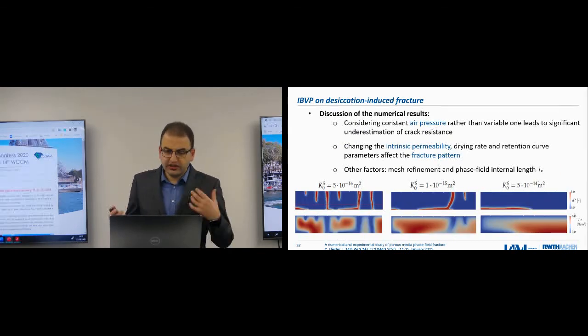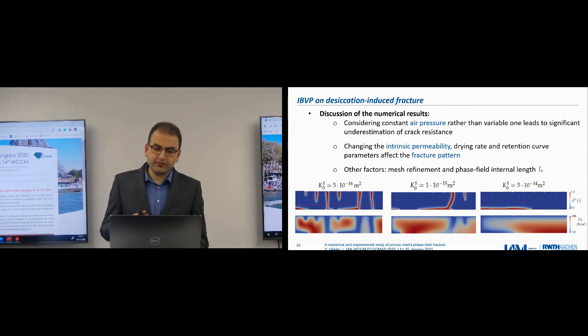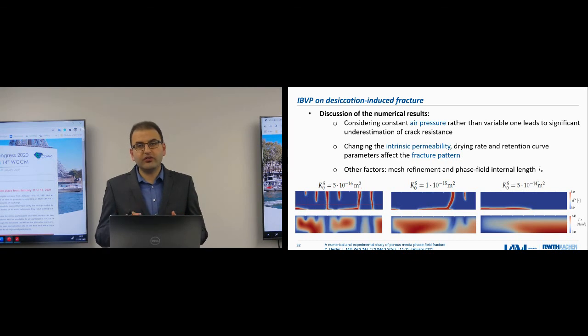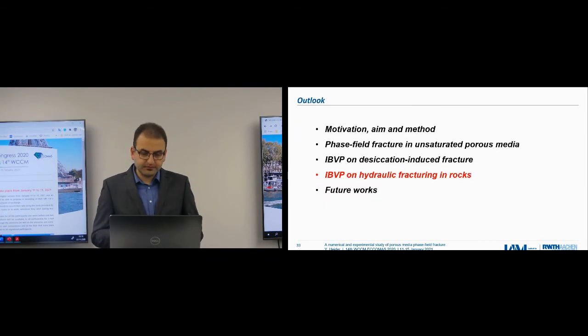In the analysis, we tested a number of issues: material parameters, different boundary conditions, and model parameters, and how all these issues affect the cracking patterns. For instance, here the permeability is a very important factor. Once we go towards very high permeability, then we will not have a lot of cracks, or maybe no cracks at all. And if we have very low permeability, just like clay, then we'll have more cracks. As you see here in this picture, you have a lot of cracks.